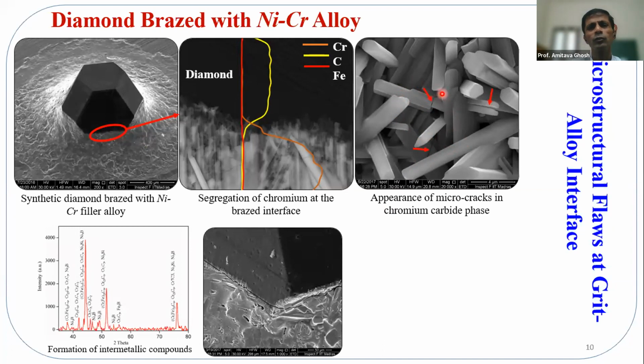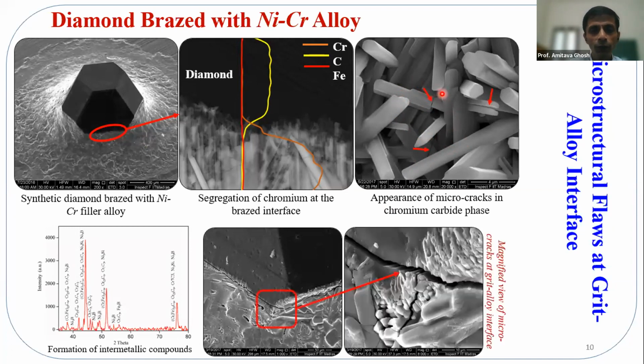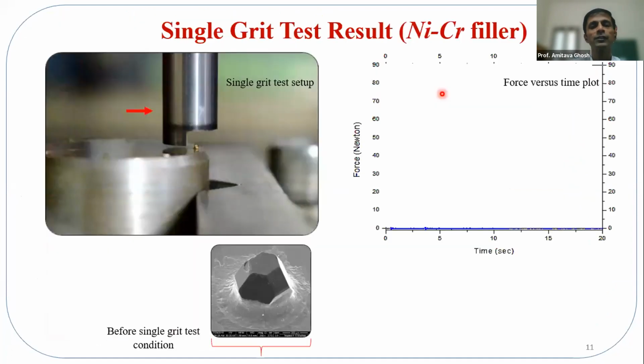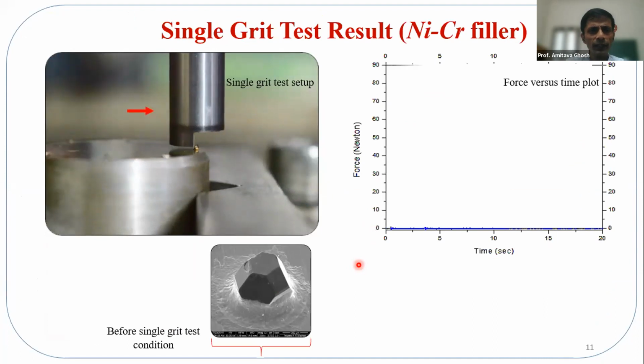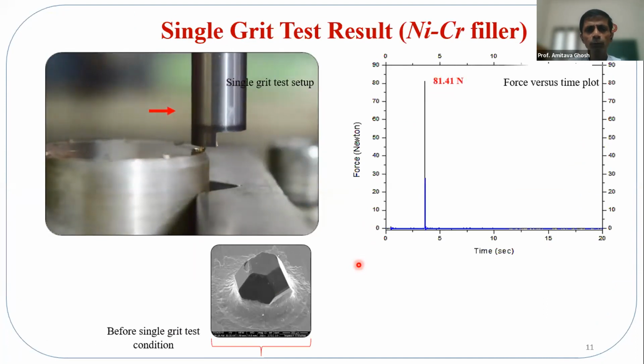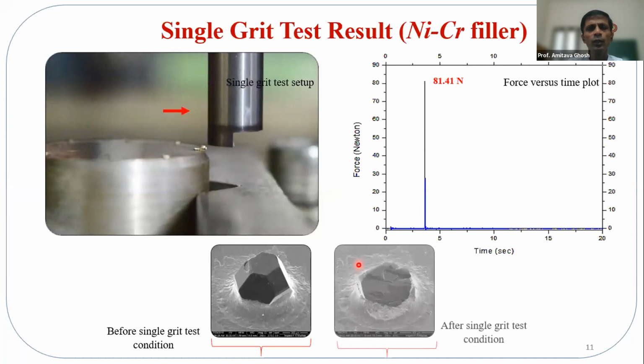That's a very nanometric opening. As such, even with this crack, the diamond can sustain a very good amount of force. So possibly that is adequate to some extent from the perspective of a grinding tool. Because when we tested the joint strength in our laboratory, we saw that this kind of small grit, a 700 micron grain, was struck with the linear motion of a carbide rod, and it could withstand up to 81 Newton.